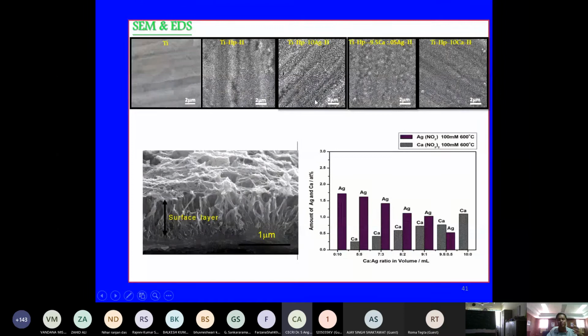You can see in this slide that because of the surface modification, we try to decorate silver as well as calcium. We try to optimize the silver, because you can also tell me that silver in large excess is always toxic. Yes, we also agree. That's why we try to minimize the silver concentration so that it can kill the bacteria, but simultaneously it should not kill the bone cells, because if cells are dead, then the implant has no use, because the patient also may die. So we need to always be very careful while optimizing the silver concentration. As I mentioned, large excess silver is always toxic in the body.